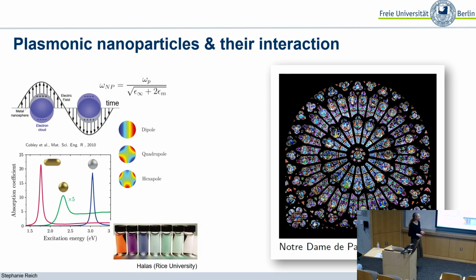The optical properties of gold nanoparticles is something that mankind has really used for many centuries. They have the ability to very strongly absorb and scatter light. And if you look at these old church windows, and this here was the one in Notre Dame, which unfortunately was lost in the big fire of Notre Dame, the very bright red color that you have in these church windows comes from gold nanoparticle inclusions inside the glass.